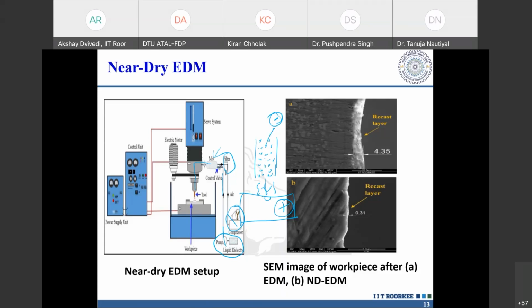Now, in this case, if the energy is lesser, or I should say controlled in a better way, you have far lesser heat affected zone on the work material. What happens with respect to material removal rate? If I have to give you a number, when I compare conventional EDM and near dry EDM at the same process parameters, with the only difference being the dielectric medium, the material removal rate is 5 times higher with near dry EDM over conventional EDM. 5 times higher. Amazing.